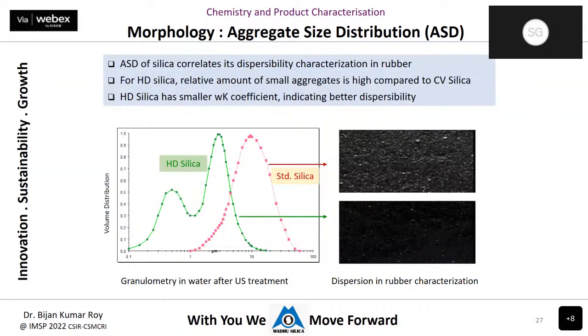Another very important parameter of silica is its particle size. Whatever silica we produce in the final form is in the aggregate form only, not the primary particle size. But when these aggregates are mixed into the rubber matrix, they disintegrate into smaller fractions. So when you measure the particle size of silica, you can see this chart. This is the standard silica, the red one, and this is the highly dispersible silica.